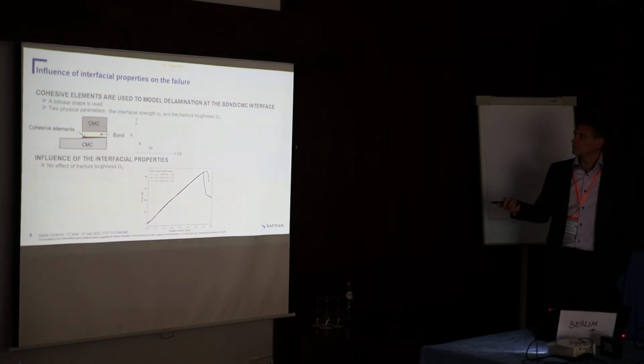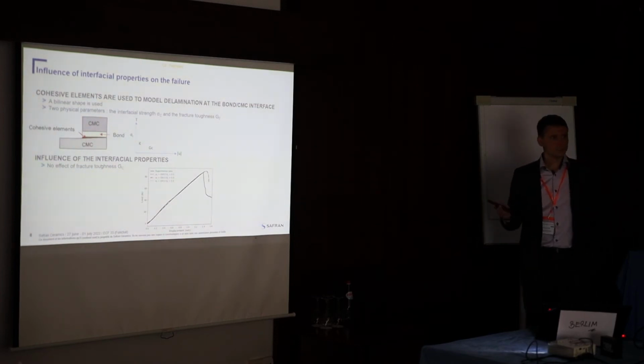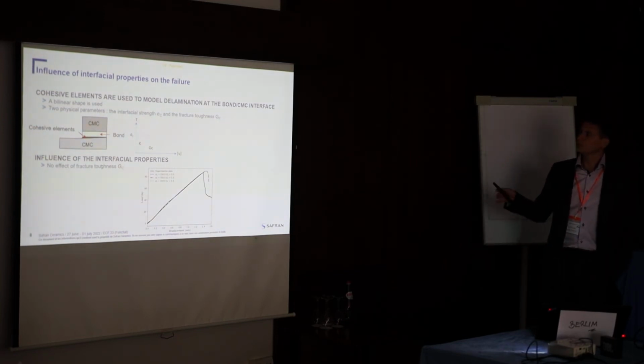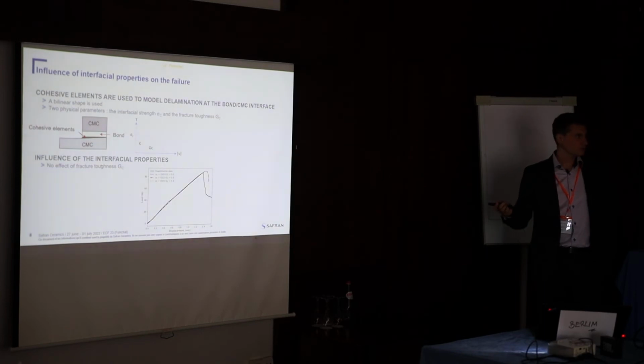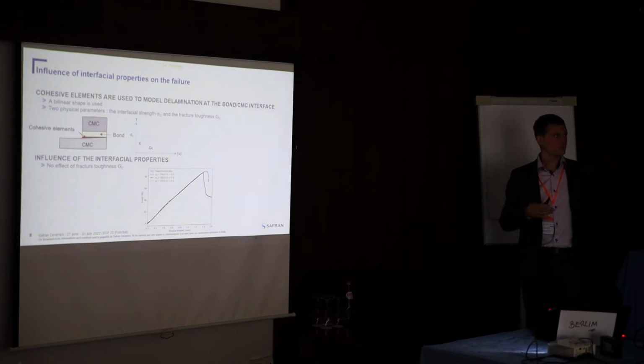We have used a cohesive zone model with a bilinear shape in order to describe the delamination at this interface. So we have two physical parameters, the interfacial strength and the fracture toughness. So we have studied the influence of both these interfacial properties on the macroscopic response. The first result is that we have no effect of fracture toughness. The sudden drop is due to the yarn failure in the CMC substrate here.